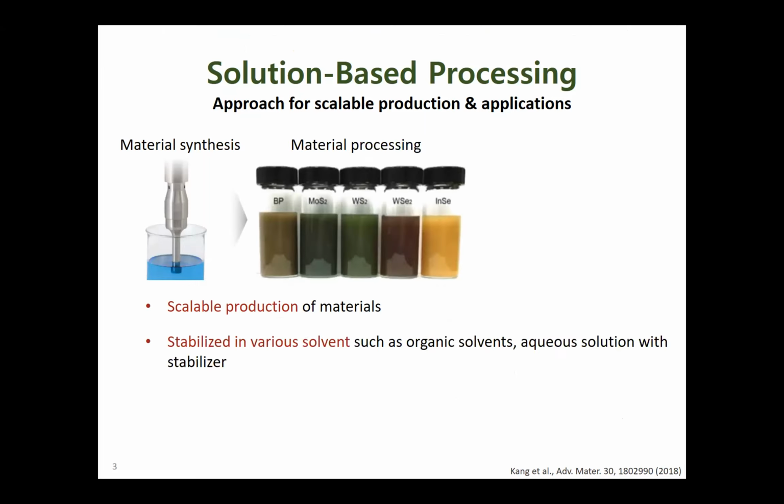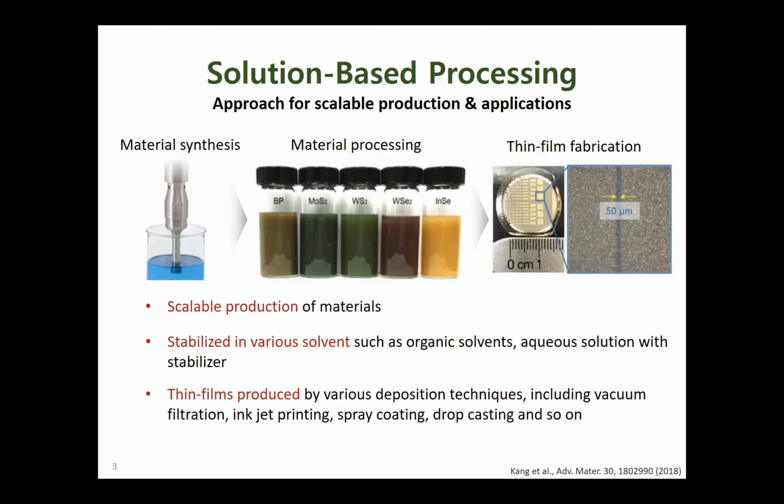It is a simple way of preparing high concentration 2D dispersions. The high throughput achieved by solution processing promotes large area thin film applications enabled by various deposition techniques such as vacuum filtration, spray coating, inkjet printing, drop casting, and so on.